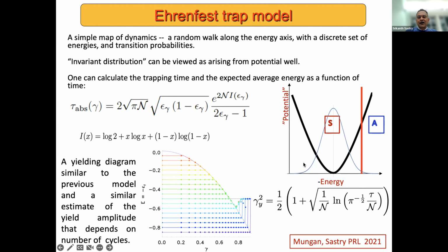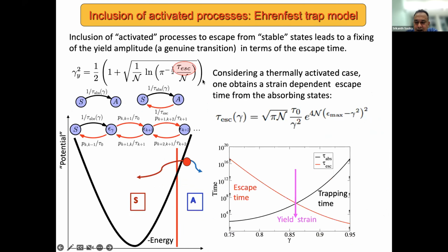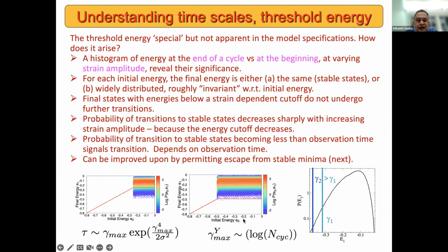And so this is then like a simple stochastic model of a random walker in a potential subject to an absorbing boundary at a value which is specified by the amplitude of shear that I'm applying. So this leads to a yielding diagram, very much like what I have shown before, as well as an estimate of the yield strain amplitude, which is looking a bit more complex, but it basically also has the same dependence that I already mentioned down here,